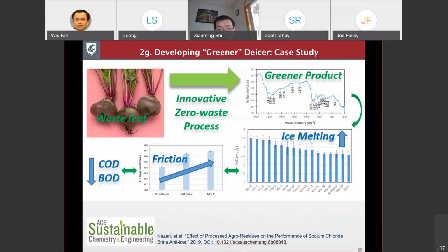Here's one case study where, instead of using beet juice, which is a common green deicer active, we want to further reduce the oxygen demand of this material. So we end up using the waste sugar beet leaves and use a patented technology to derive green chemicals out of the waste leaves. And then we blend it with brine, of course, in this case reducing the chloride loading, improving the ice melting friction and reducing the oxygen demand compared with the typical green deicer out there, which is a blend of salt brine and sugar beet juice.